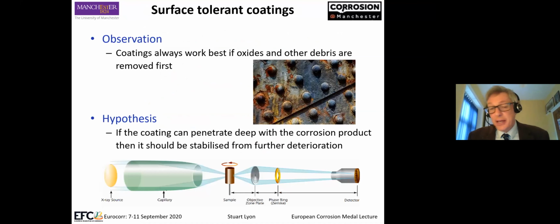So my final example is surface tolerant coatings. Coatings always work best if oxides and other debris are removed first. So if you try and paint this, you know it's not going to work. You need to get rid of all that rubbish that's on the surface. So the hypothesis, on the other hand, is if we can somehow penetrate into that rusty, horrible mess there and bind it all together, then perhaps it can be stabilized from further deterioration.